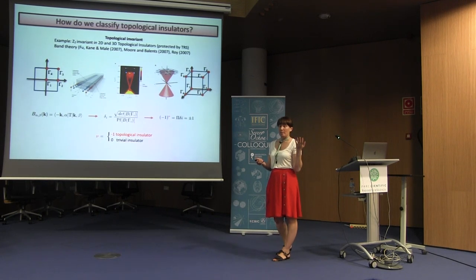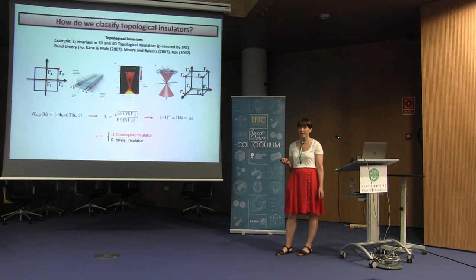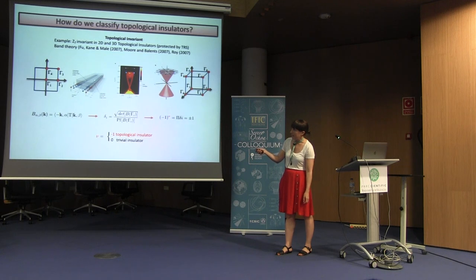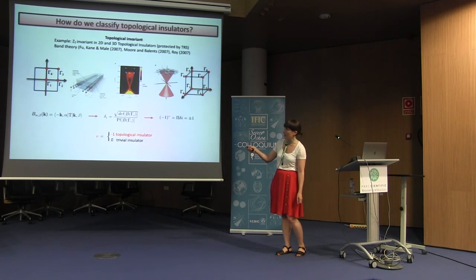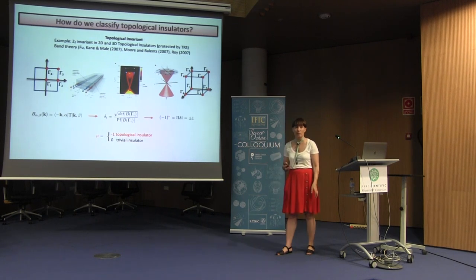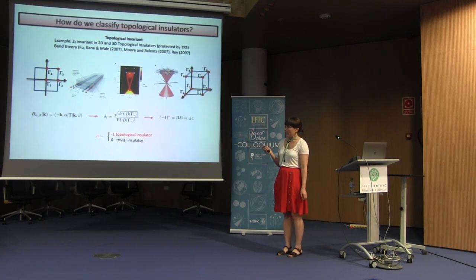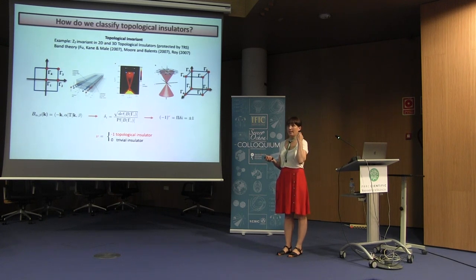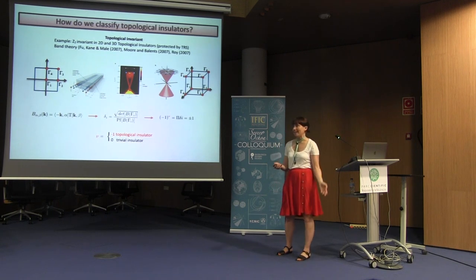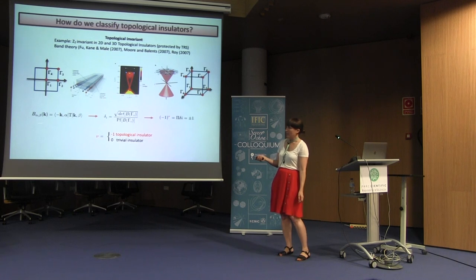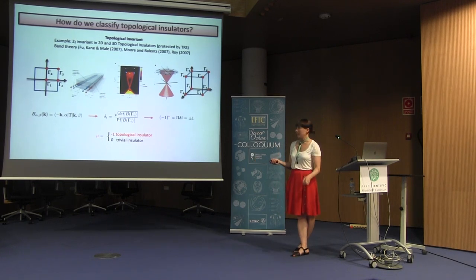In 2D, we have a maximum of 4 high symmetry points. In 3D, we have 8. And as I show here, whenever we have a topological phase, in 2D we have edge states, and in 3D what we find is surface states with a conic dispersion. The way to calculate the topological invariant is by looking at the high symmetry points of the band spectrum and calculating the parity product with the symmetry that we want to analyze. In this particular case, it's time reversal symmetry. So we have this matrix, we calculate the parity product at the high symmetry points, and if the parity product is odd, we have a topological insulator, and if it's even, we have a trivial insulator.